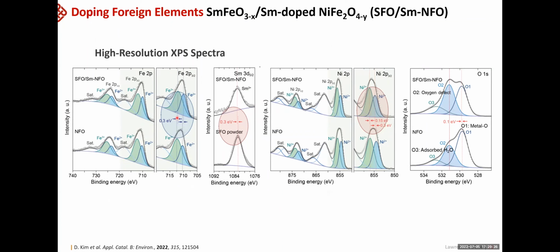As you can see in this zoomed area, we see the negative peak shifts of the iron species, whereas the samarium and nickel show positive shifts, which means they are actually in a very strong electronic interaction. And also the oxygen spectroscopy shows the highly enhanced oxygen vacant sites, defective sites.